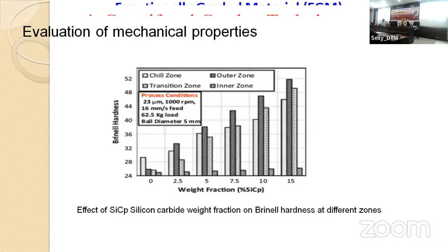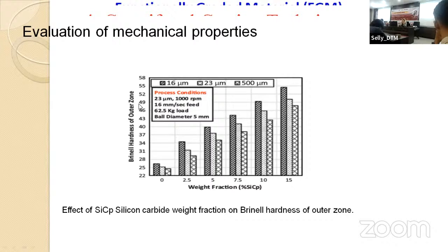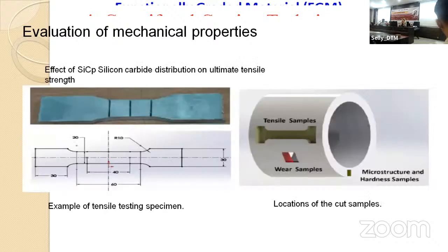Look at that. The Brinell hardness changes according to the weight fraction. What does it mean? The inner zone, outer zone, and transition zone have different Brinell hardness. Yes, it's expected, of course. And you can see just the outer zone, because the outer zone is the most crowded and hardest area for us. The Brinell hardness of the outer zone differs with the size of the silicon carbide particles. I want to show you it is related to the weight fraction, and we can change the hardness of the tubular sample according to functional graded materials by using the centrifugal casting method.